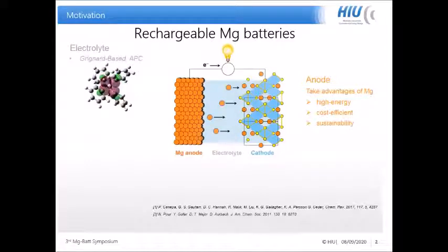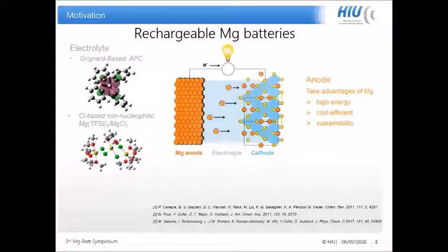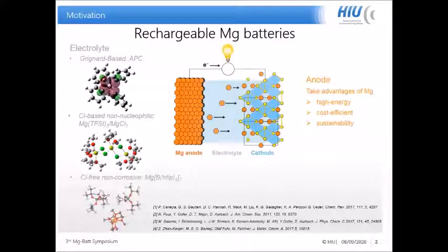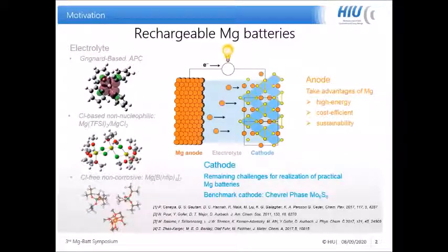For example, this Grignard-based APC electrolyte, which is widely used in the community, and this non-nucleophilic electrolyte, which is compatible with the sulfur cathode and also the organic cathodes, and also this chlorine-free magnesium electrolyte with a broad electrochemical window, and this allows us to couple the metallic magnesium anode with a high voltage cathode material. So there's no doubt that the electrolyte has been the most advanced part in the magnesium battery technology, and in comparison, the cathode development is still in a very early stage, I would say.